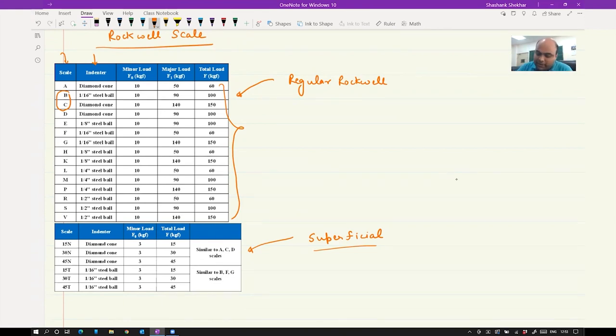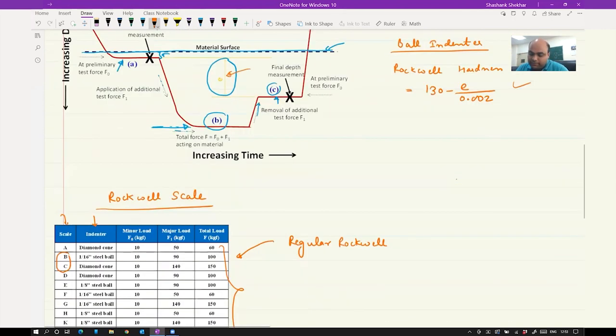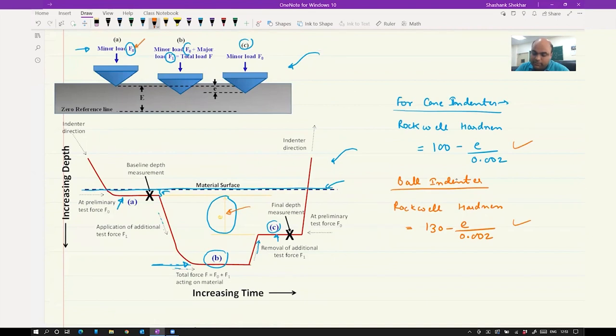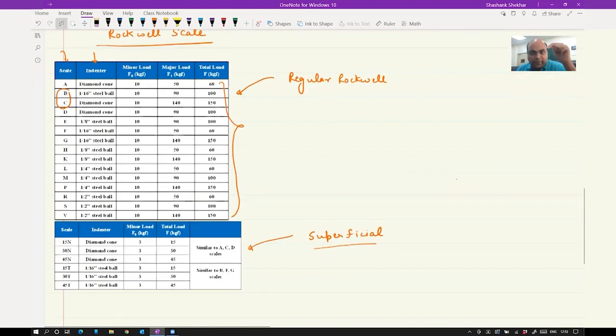So if you use B scale, the indenter is going to be a 1/16 inch steel ball. And if you use C scale, it is going to be a diamond cone with 120 degree angle. In all the cases, you are going to have a minor load, F0, of 10 kgf. Then we also apply a major load onto the minor load. That will vary depending upon the scale. So for A scale it is 50, for B 90, and C 140. And then total load is the summation of minor load and major load, which is given like this.